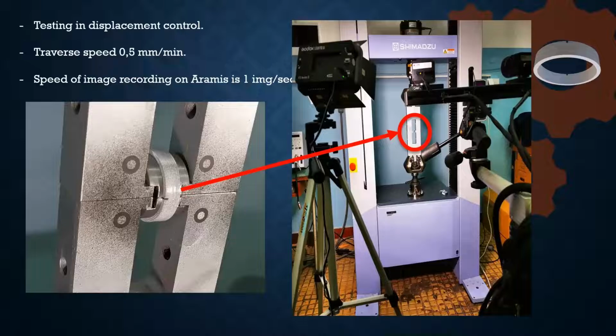The test conditions were as follows. The speed of the upper traverse was 0.5 millimeter per minute, and the recording speed was 1 image per second.